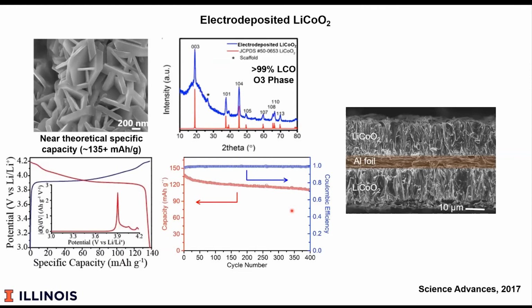Okay, so we quickly gave up on using the foams as scaffolds for the cathode, as I had shown you, and we discovered that indeed we could grow these in fairly dense form. This happens to be an aluminum foil, just false colored here, and then lithium cobalt oxide. This is 10 to 15 microns thick. I'll show lots of examples in the subsequent slides.